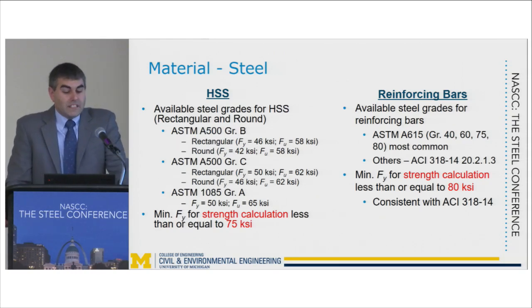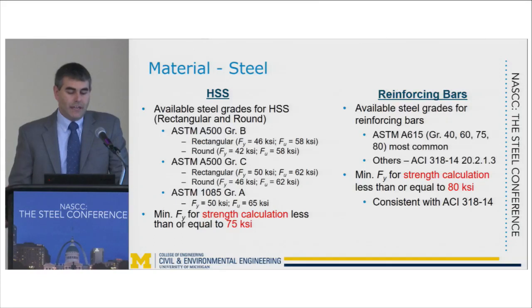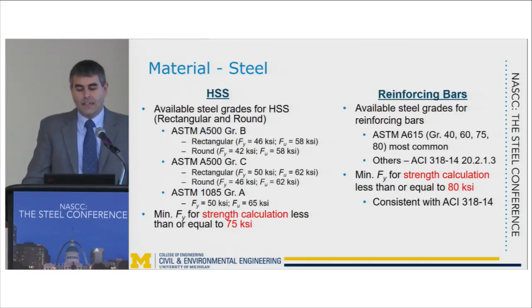Now, if we consider the materials that are involved, obviously the steel HSS members, the available grades that we have are ASTM A500 grade B and C, and ASTM A1085 grade A. The thing to keep in mind in terms of the HSS members is that your minimum yield strength for your strength calculation has to be taken as less than 75 KSI.